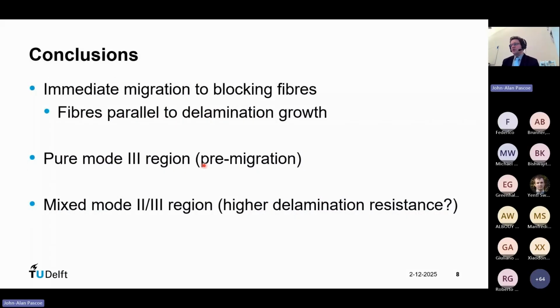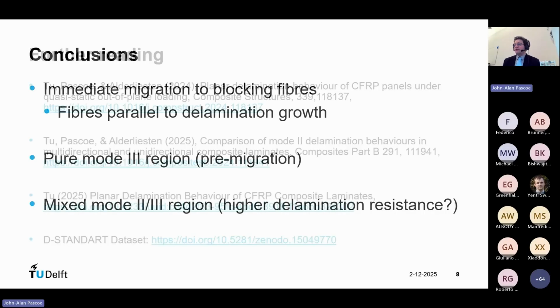So in conclusion, what we see, if the fibers are not aligned with the delamination growth direction, or the preferential growth direction, we immediately get migration to the blocking fibers, so where the fibers are aligned in the growth direction. We see a pure mode 3 region pre-migration, so that explains why we immediately get this migration happening. And there's a mixed mode 2-3 region where we see this matrix cracking. And we could imagine that this matrix cracking, of course, also takes energy and is therefore slowing down the delamination growth. And so we have higher delamination resistance. So that's very briefly the findings.